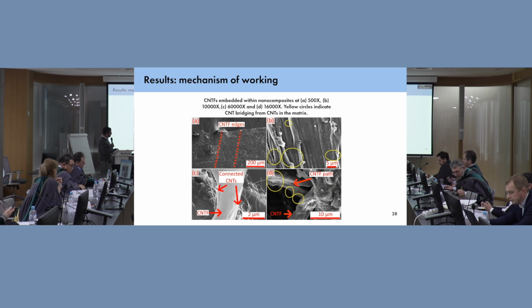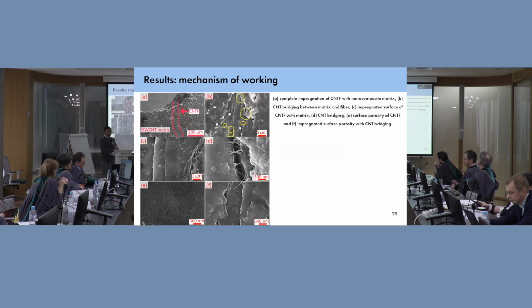And we see that all the CNTs which were in the matrix were adhering quite well to our carbon nanotube fiber. So again, some additional images just in case this was not clear. Our CNTF here, we have a lot of CNT bridging between the matrix. This is generally what the porosity looks like for our surface of the carbon nanotube fibers.